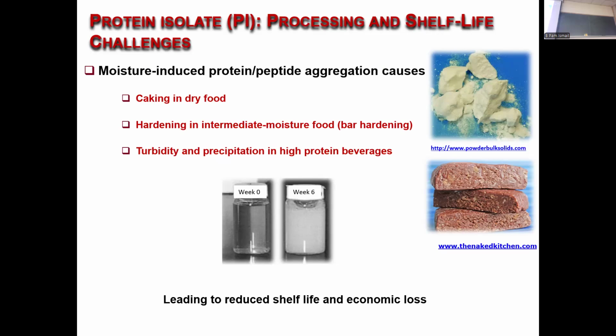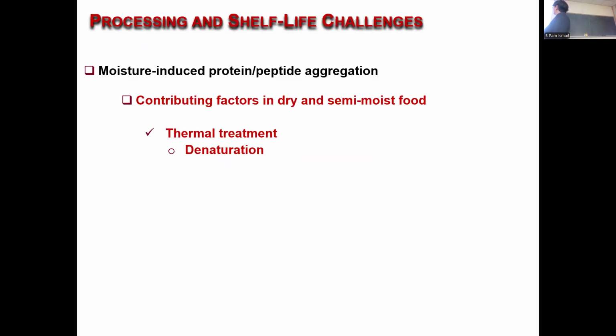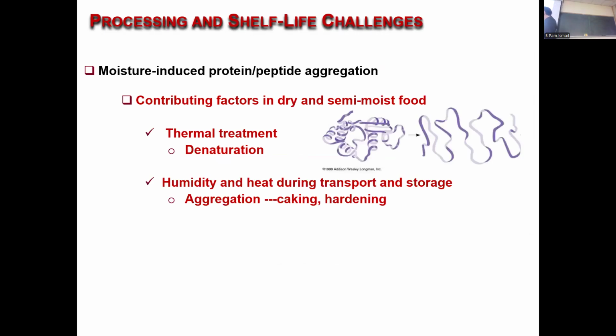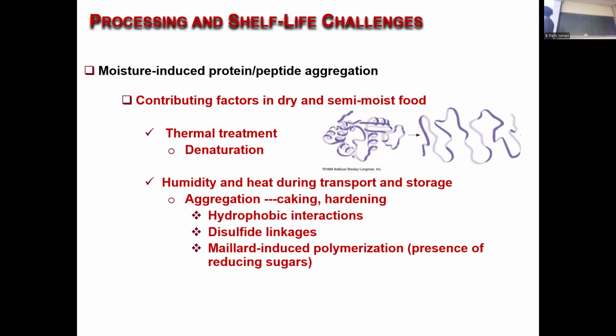There were a lot of studies. Our former colleague Ted Labuza, who passed away 2 years ago, did a lot of research with hydrolyzed whey protein, and all the bars hardened over time. And when you prepare a beverage, you get cloudiness, turbidity, gelation over time, even with hydrolyzed protein. So thermal treatment, denaturation, aggregation cause caking, hardening, or gelation in beverages due to hydrophobic interaction with denatured protein and disulfide. Even if you break them into peptides, sulfide groups are there, so they can reform through disulfide interchange. And if you have reducing sugar, you form Maillard-induced polymerization, contributing more to the aggregation.